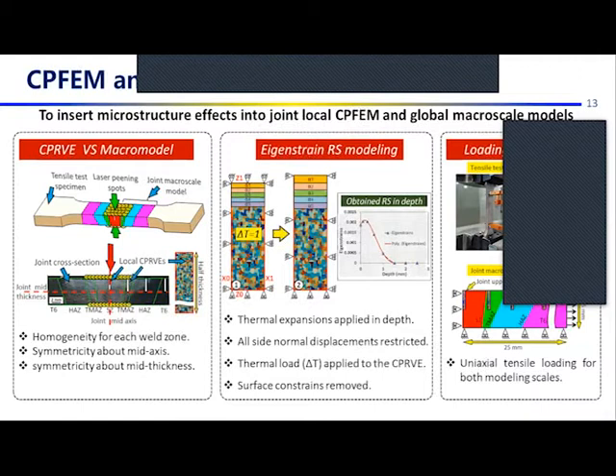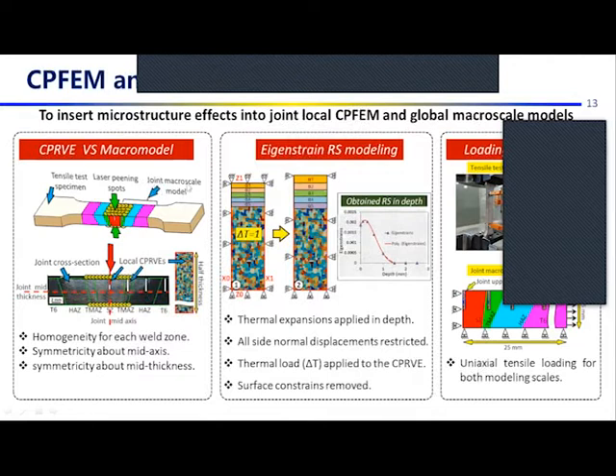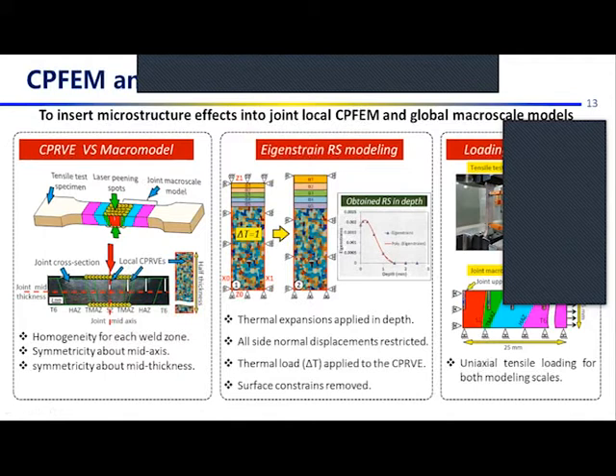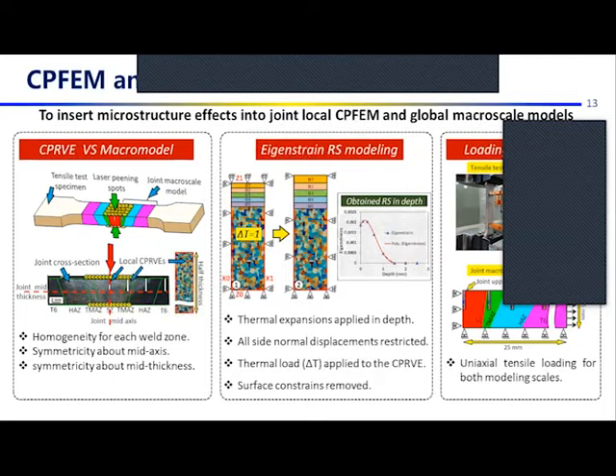For the CPFEM meso-scale and micro-scale modeling, we consider the homogeneity of mechanical properties for each welding zone and the symmetry about the mid-axis of the zone and sheet thickness. This leads to the development of a joint micro-scale model — the half cross-section — and CPFEM RVE models for each zone covering half of the thickness. We have an eigenstrain model to simulate laser peening-induced residual stresses and loading applied to the CPFEM models and macro models to obtain joint local and global mechanical properties.